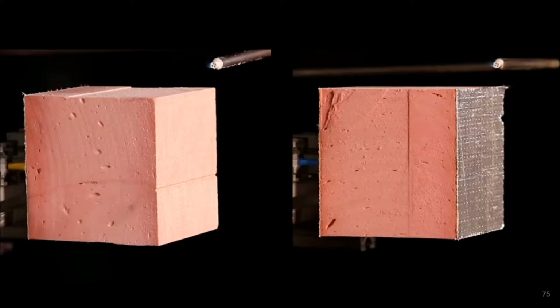On the right, for the sample which is protected by a foil facer, which in this case is only about 25 microns thick, so 25 thousandths of a millimeter, again, we won't see any ignition. We'll also notice that we won't see any bubbles forming in the foil facer for the K15 product. This is obviously because the foil facer is perforated, and the flammable gases can easily get out of the sample, so to speak. So now I'll let it run.